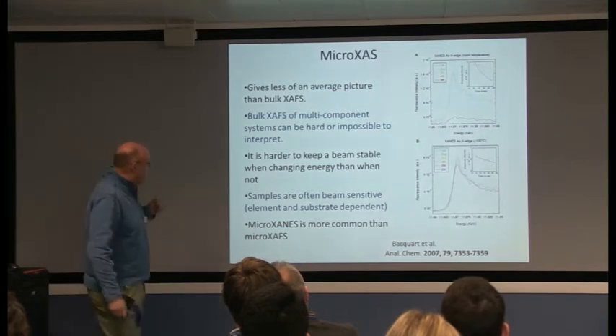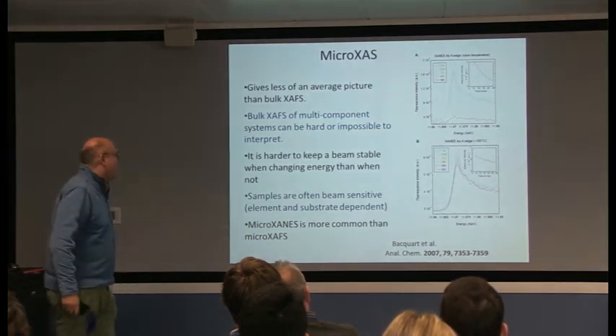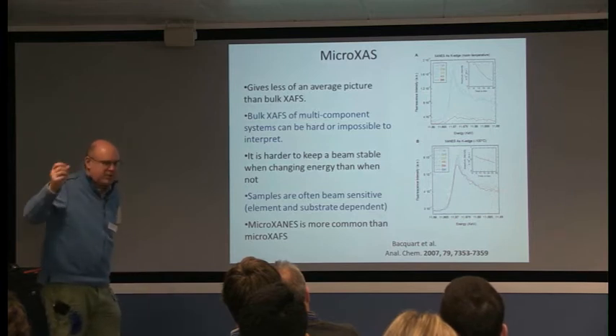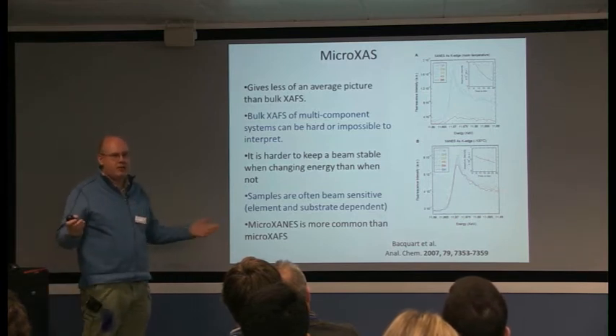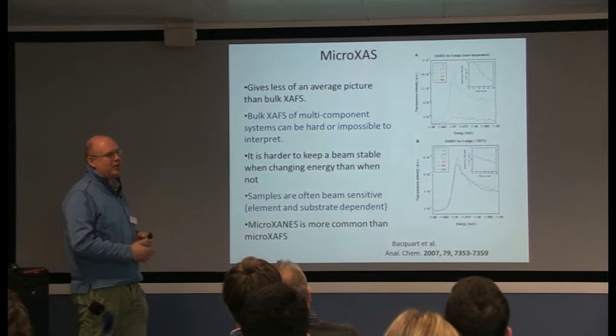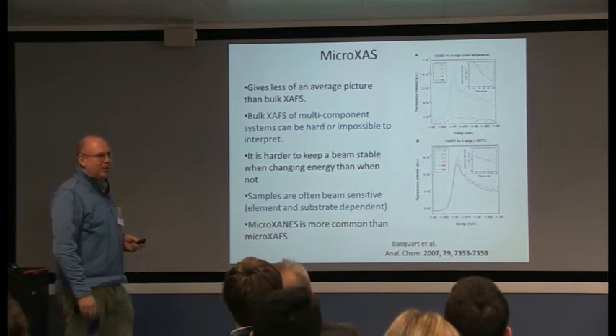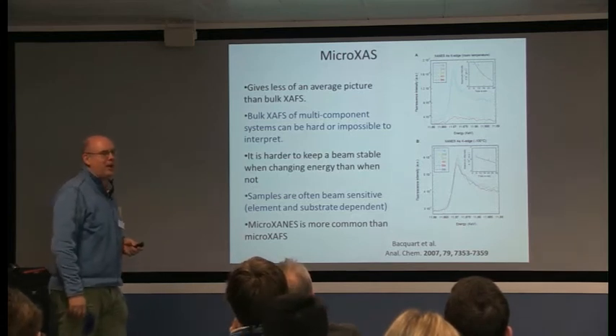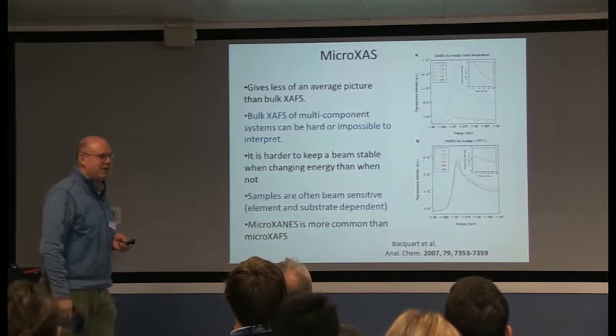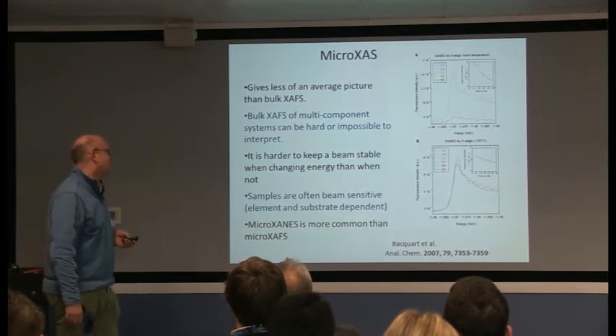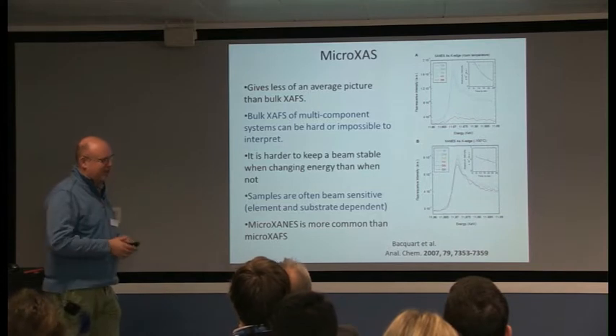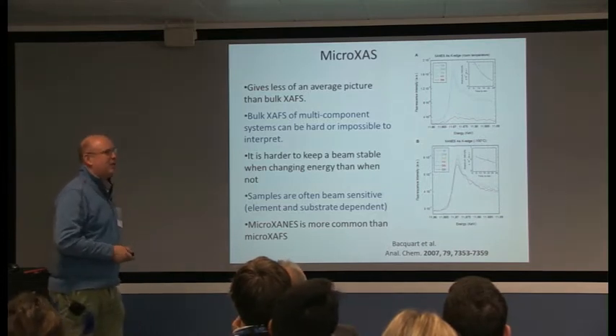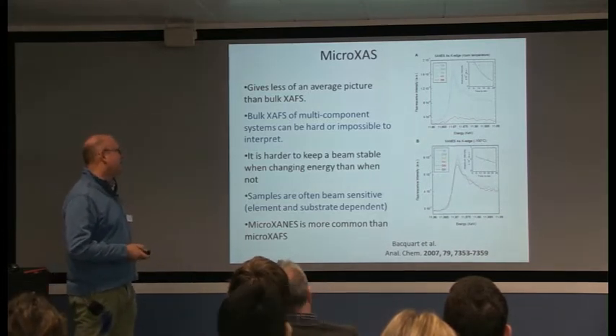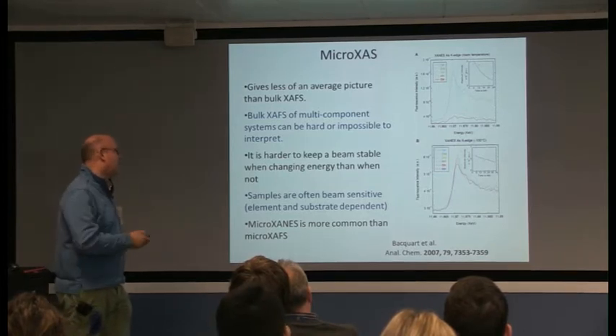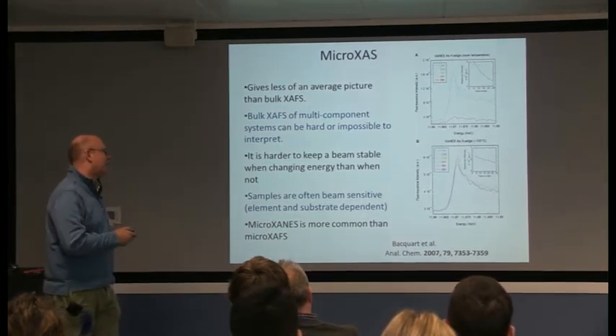Micro XAS - why do people do it? Well, it gives less of the average pixel than bulk XAS. Bulk XAS of multi-component systems is really hard to look at. If you get to more than 3 components, disentangling it even by linear combinations can be hard. Ab initio is almost meaningless at the 3-component stage. So if you've got something like soil, micro is often the way to go, because you can look at the individual components and then use those perhaps to linear combination fit your bulk XAS spectra, or something like that.